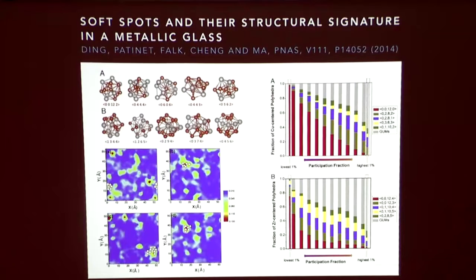You can characterize all those different topologies of bonding, and then ask whether the ones more like icosahedra are harder and more difficult to deform, and the ones more disordered are easier to deform. That does generally tend to be the case—these very disordered structures tend to be more deformable and correlate with soft modes more than the more ordered icosahedra-like structures you see in metallic glasses.